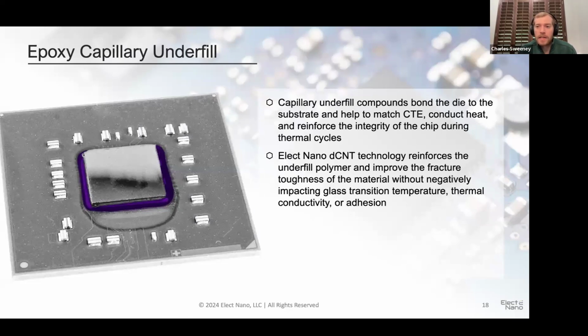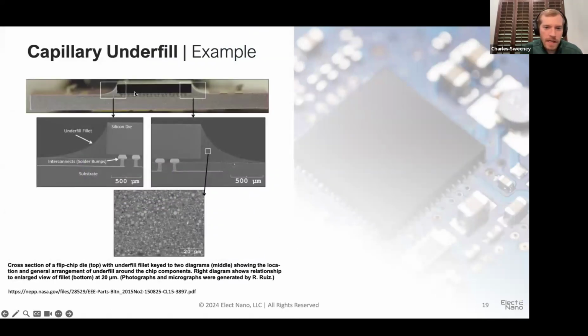The stresses are very high here, and so the fatigue ends up being a really critical component. Fatigue and adhesion of that underfill to the two interfaces dominates the ability of the underfill to do its job well. This is a cross section looking at an underfill. You'll get a capillary edge here, and then the flow of the material underneath that chip. You can see the bumps here. If you zoom in, you can see all the little silica particles that are used to tightly pack the rest of the volume so that it has a very low CTE.